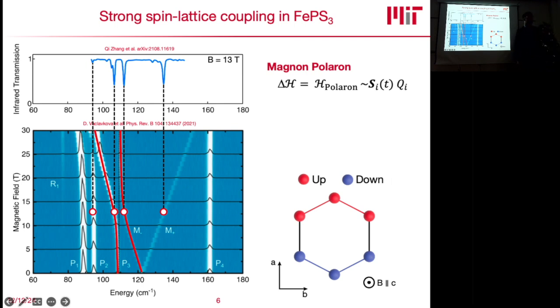These modes usually do not have infrared activity. However, they actually start appearing in infrared transmission, as little dips in your infrared transmission. And this means that your magnon, which is infrared active, lends infrared activity to these modes. So they start becoming these new hybrid modes that people like to dub a magnon polaron. And if you then write down this very simple Hamiltonian here, you basically get the spin coupled to the lattice. So this is usually my terminology: spin and lattice means Q.